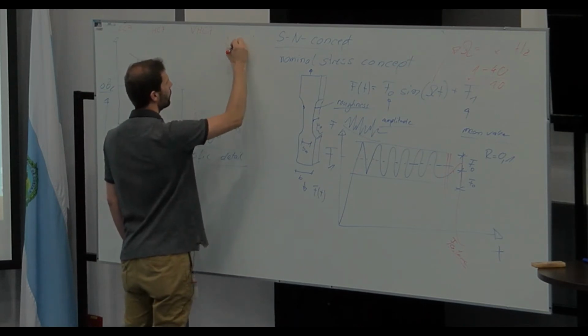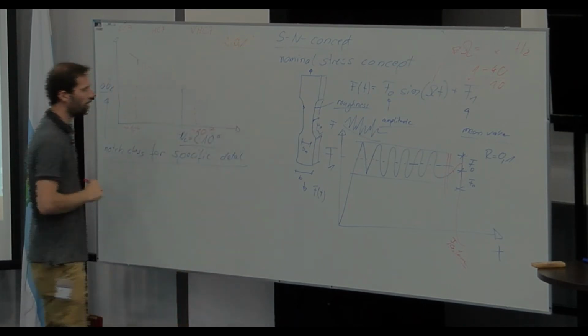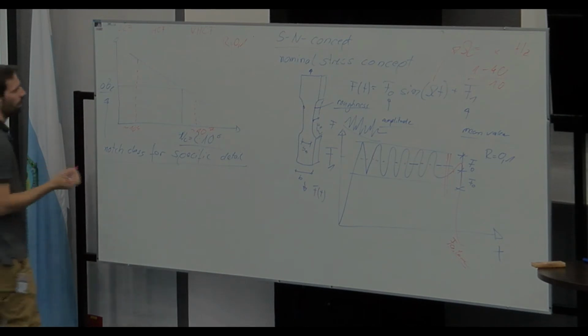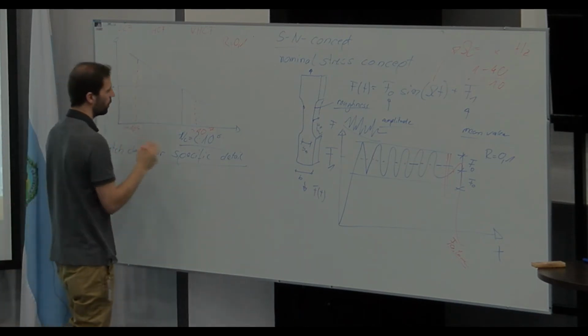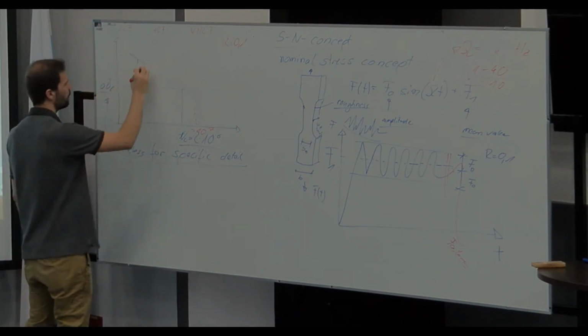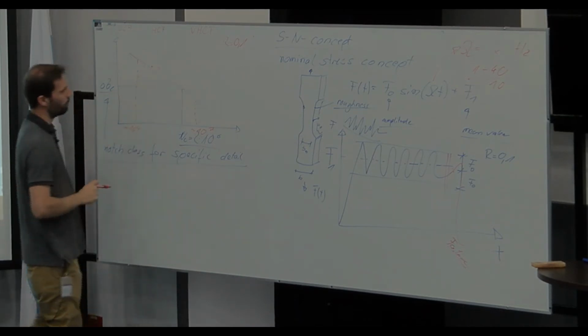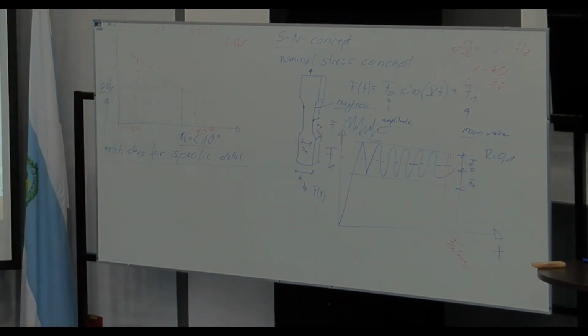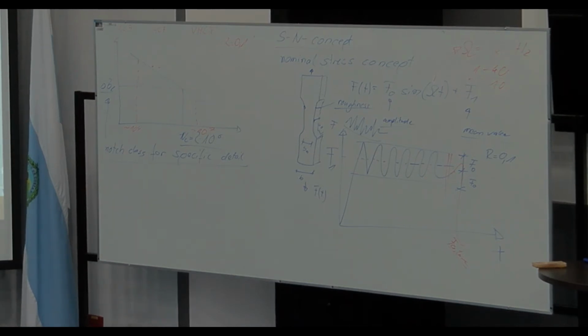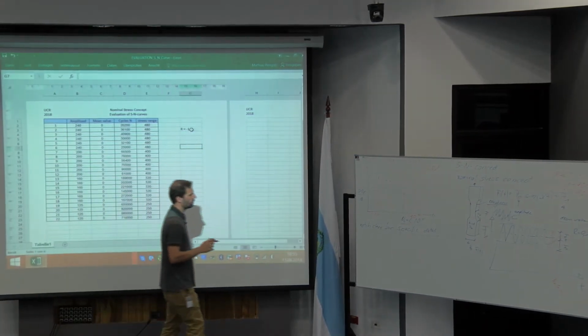By applying an R value of 0.1, as we do in our procedure, we use some horizons. And at these horizons, we always apply 3 to 6 tests. At first, we have to define our first horizon.